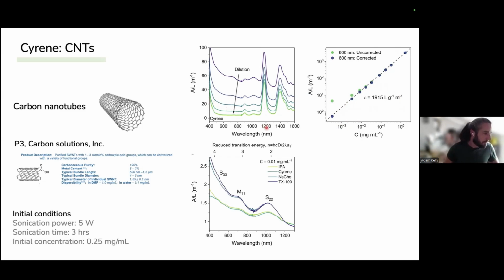Then we work with something called the reduced transition energy. The reason we plot against reduced transition energy is that peaks around 2 are associated with semiconductor transitions, peaks around 3 are associated with metal transitions, and peaks around 4 are the semiconducting 3-3 transitions. So this tells us that the majority of our dispersion, when we create this in Cyrene and sodium cholate, is large bundles of primarily semiconducting nanotubes.